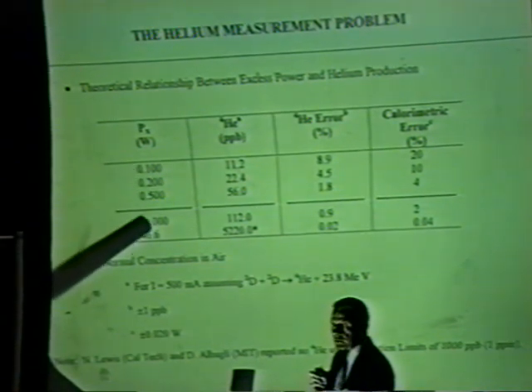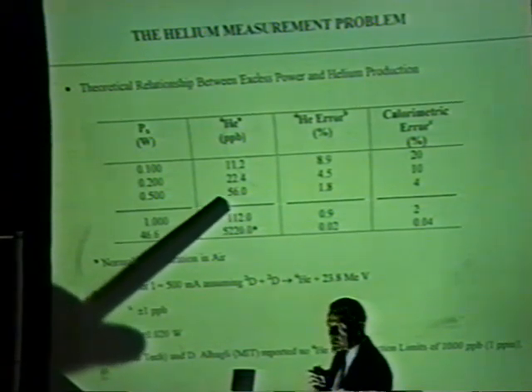And then this shows the same things for 200 milliwatts. Most of my experiments have been somewhere between 100 and 500 milliwatts. I've never seen excess power in my experiments larger than 500 milliwatts. So at 500 milliwatts, you could expect 56 parts per billion helium. Your percent error is going to be 1.8%, and calorimetric error would be 4%.